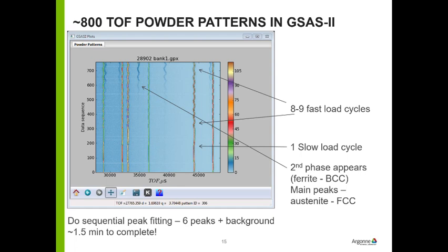And during this process, actually another phase showed up because the action of that induced the phase change. Actually, what it did is if you look really closely at this, these peaks are here at the beginning, but they're very broad. So what actually happened is that it crystallized the second phase to make it more apparent in the powder pattern.